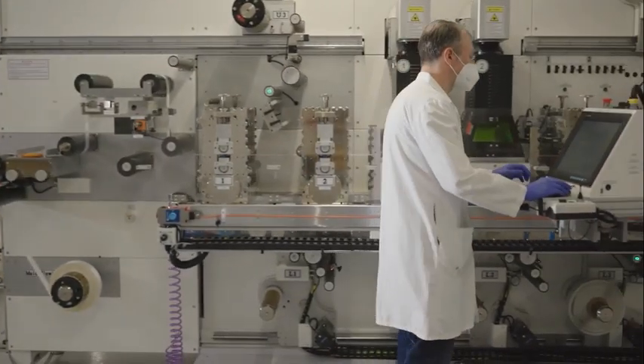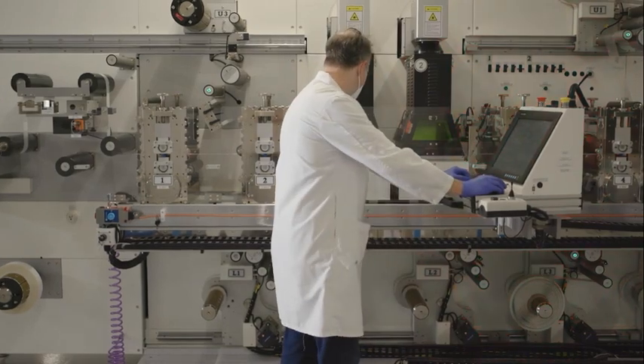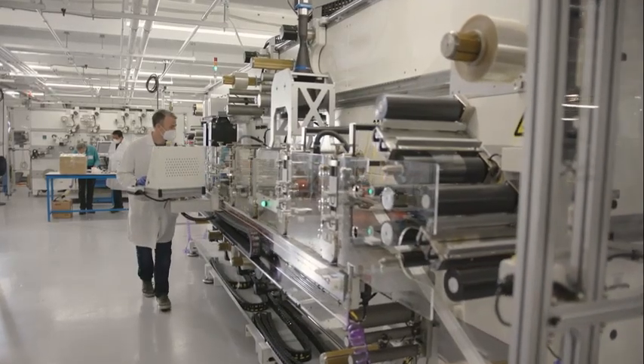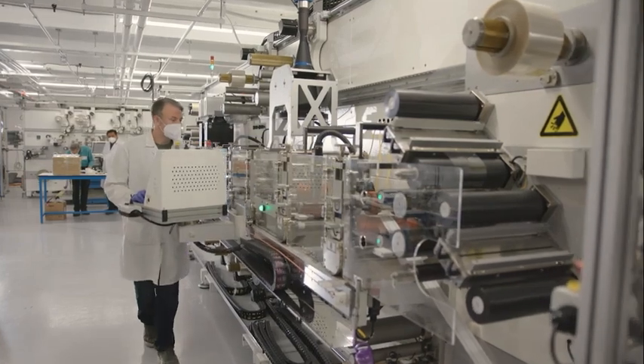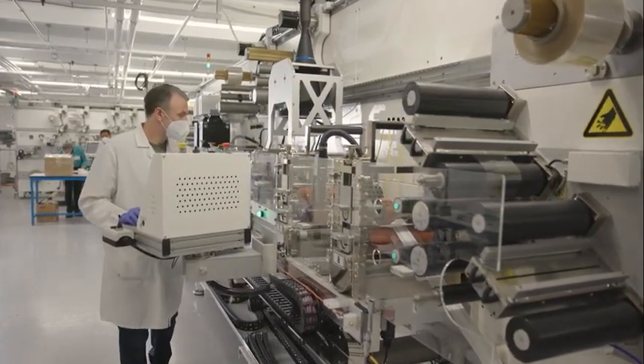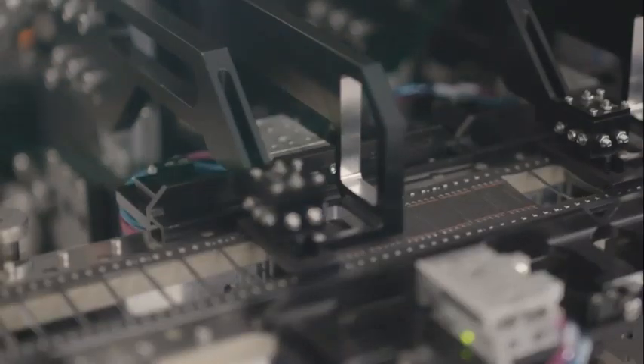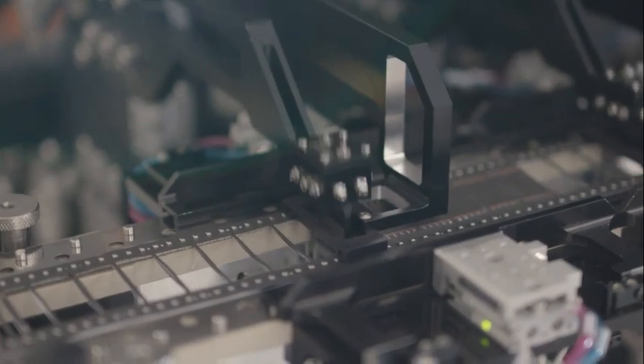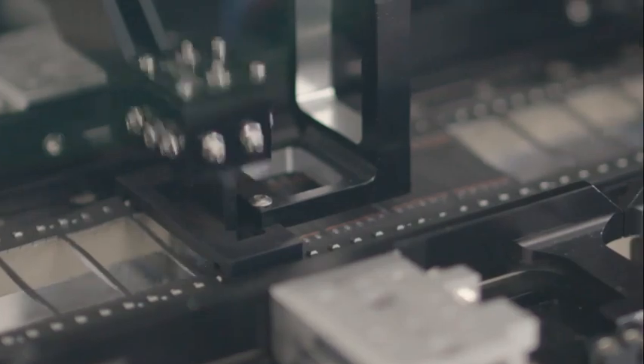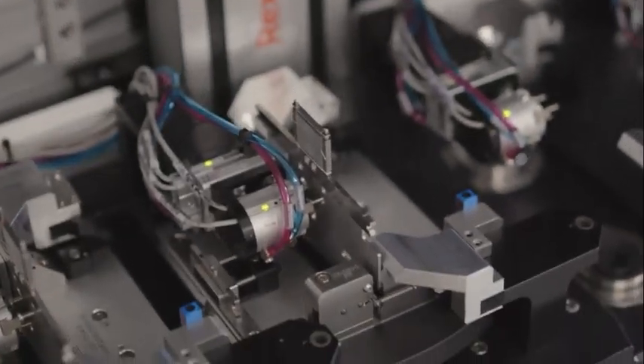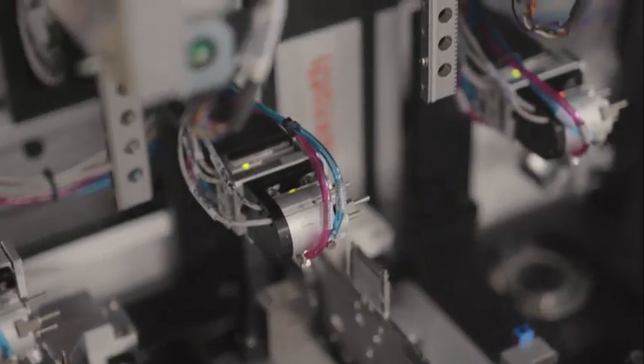We've applied an equally innovative approach to developing a proprietary roll-to-stack cell assembly. This is that drop-in approach, a replacement for conventional wound cell assembly. An inline tool precisely laser patterns electrodes and separators, which are then fed directly to a high-speed stacking tool. This provides better spatial efficiency than the jelly roll method. More importantly, it enables us to incorporate an anode with silicon as the only active lithium cycling material into a lithium-ion cell. Battery packaging and formation is the last stage of the production process.